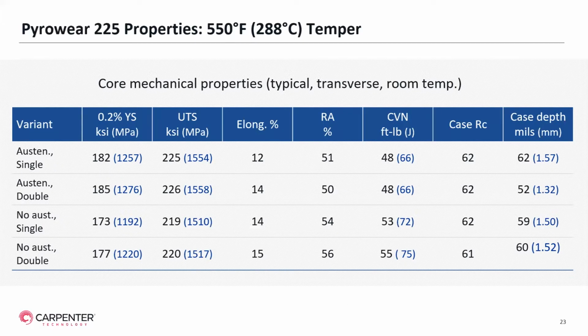In this slide, we show actual core mechanical properties, again, typical and in the transverse orientation, taken at room temperature, for those 4 variants that I just made reference to, where we gave it an austenization before tempering, or we did not, and either single or double tempering. What you can see here is that if we do give the material an intermediate austenization after carburizing but before tempering, it does result in slightly higher yield strength and ultimate tensile strength versus not giving it an intermediate austenization.